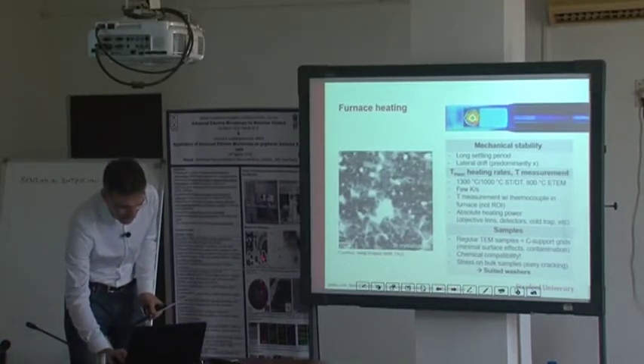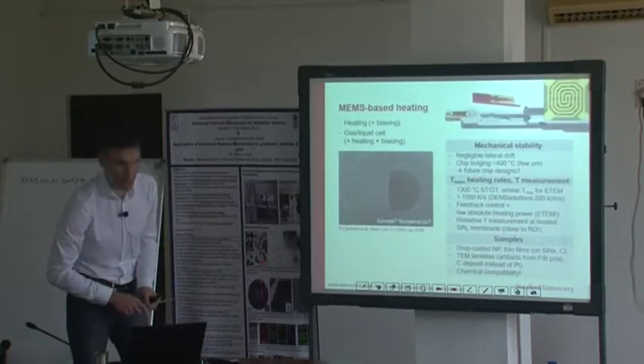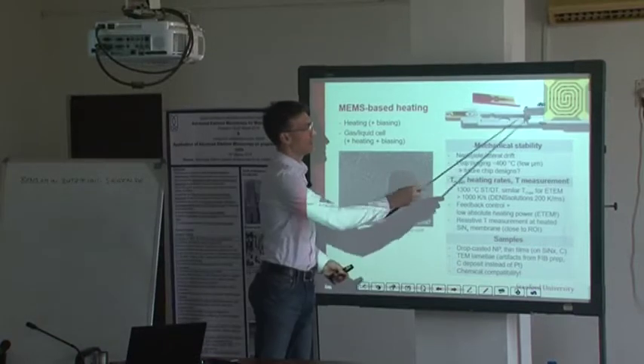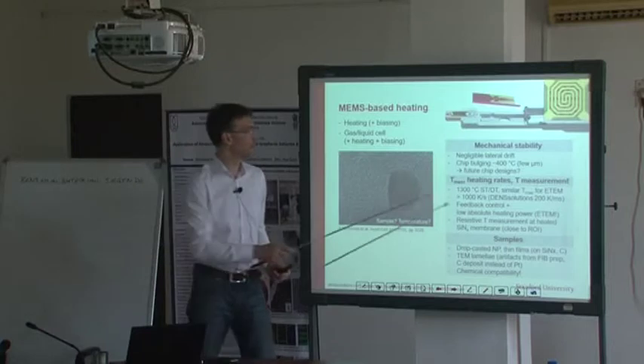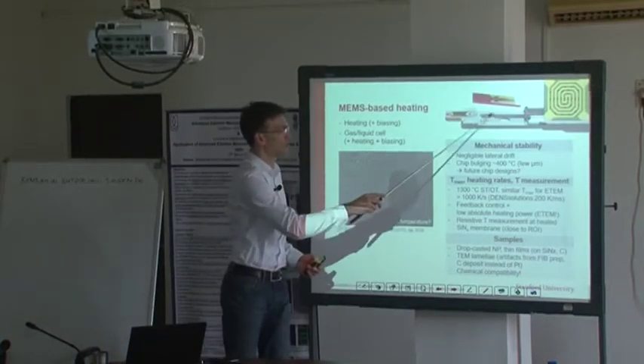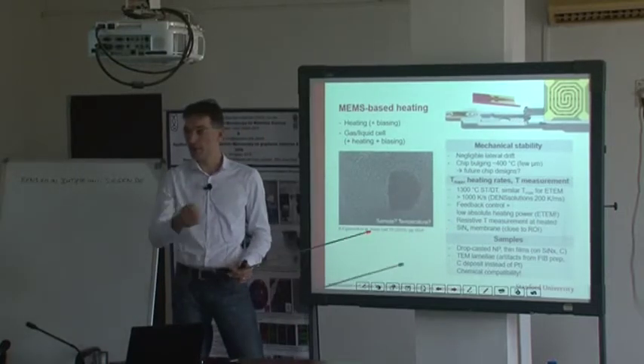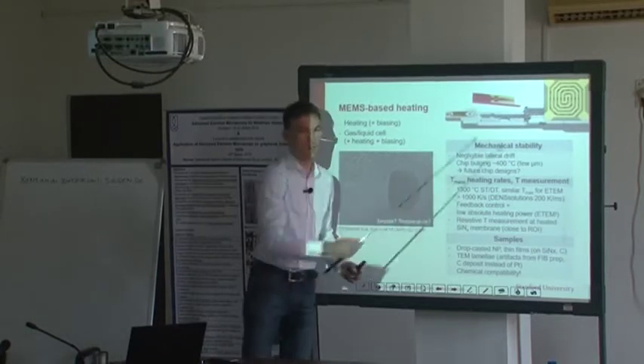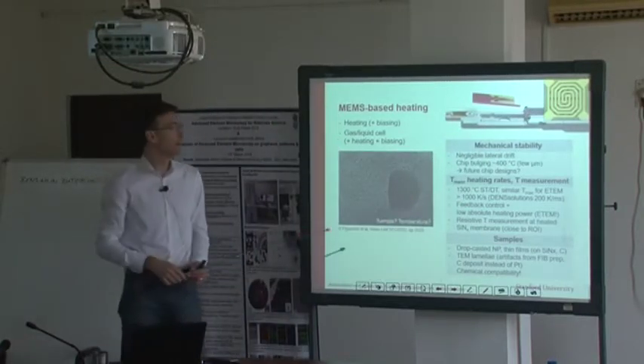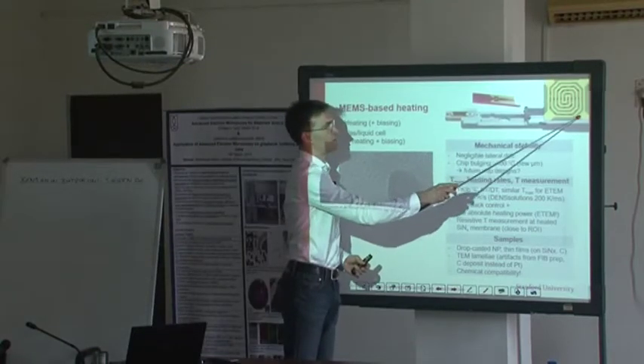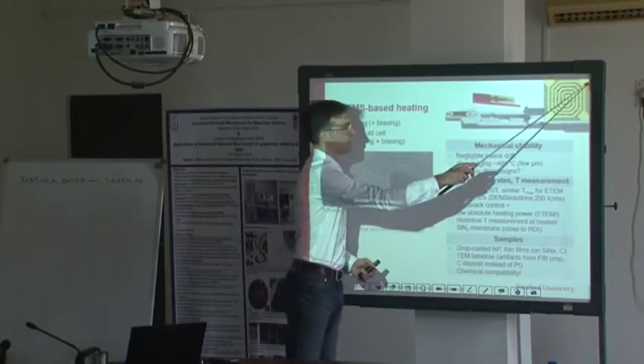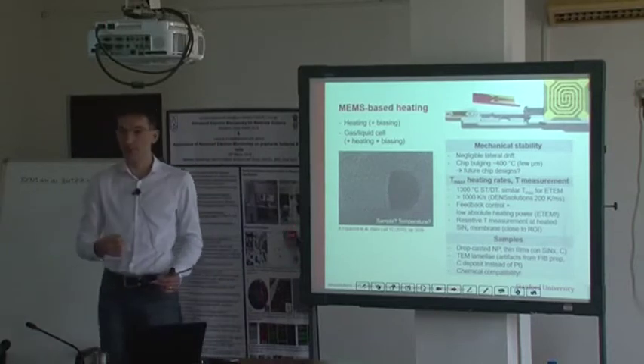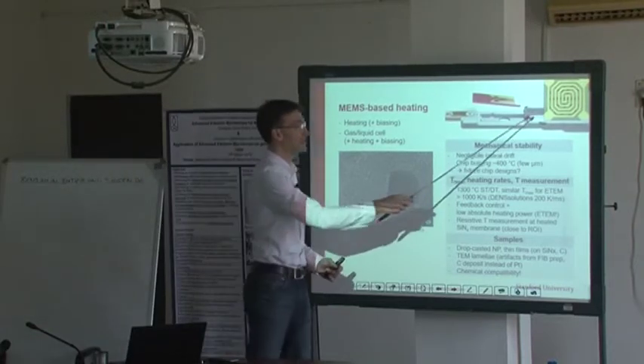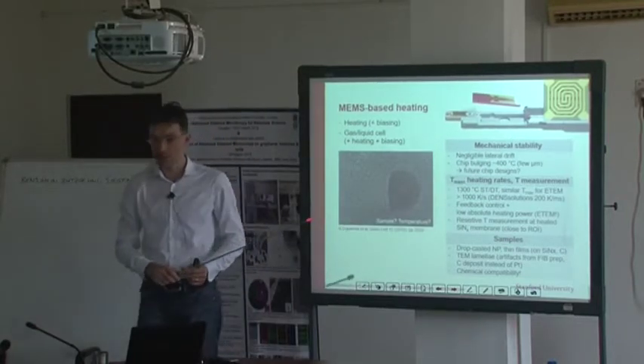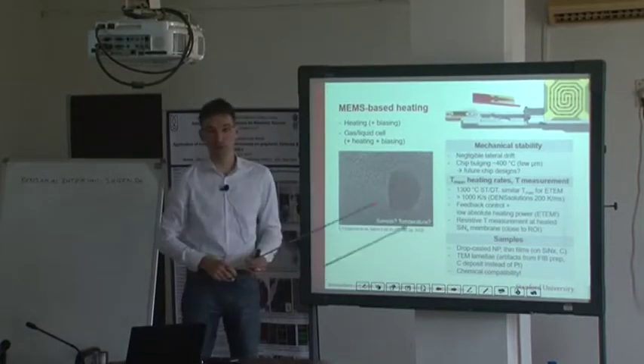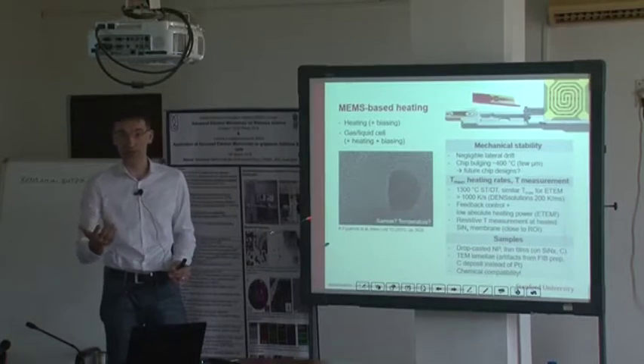And there's another way to heat in a transmission electron microscope, and this is to utilize MEMS-based heater chips. In this particular case, this is the DENSsolutions heater chip. So you just introduce this heater chip, you contact it, and you simply run a current through such a metallic nanostructure. And due to the resistivity of the nanostructure, heat evolves. They apply a current to introduce the heat, and with another two ports they measure the resistivity of the structure, and the resistivity depends on the temperature, and so they are able to calibrate this temperature. And for high vacuum experiments, this preset temperature corresponds very well to the measured temperature which we got from our diffraction experiments. So this is quite good.